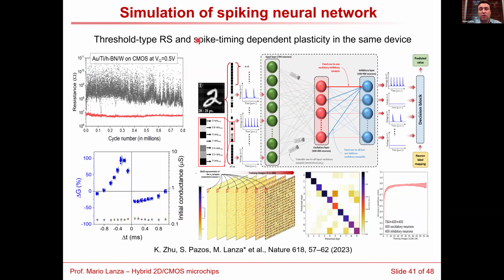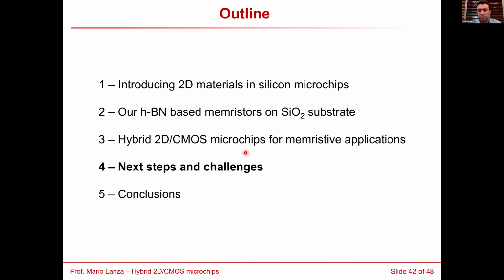Let me also say that when we reduce the gate voltage, we can also observe threshold resistive switching and spike time dependent plasticity. It's not the nicest spike time dependent plasticity in the world, but we have made fittings and also an electrical model with SPICE and also system level simulation of a spiking neural network. And we observe quite decent performance for this type of devices. So I think this is something remarkable, especially because it's achieved on a microchip, and this already has a relatively high technology readiness level compared to many other articles that report resistive switching devices on silicon oxide.